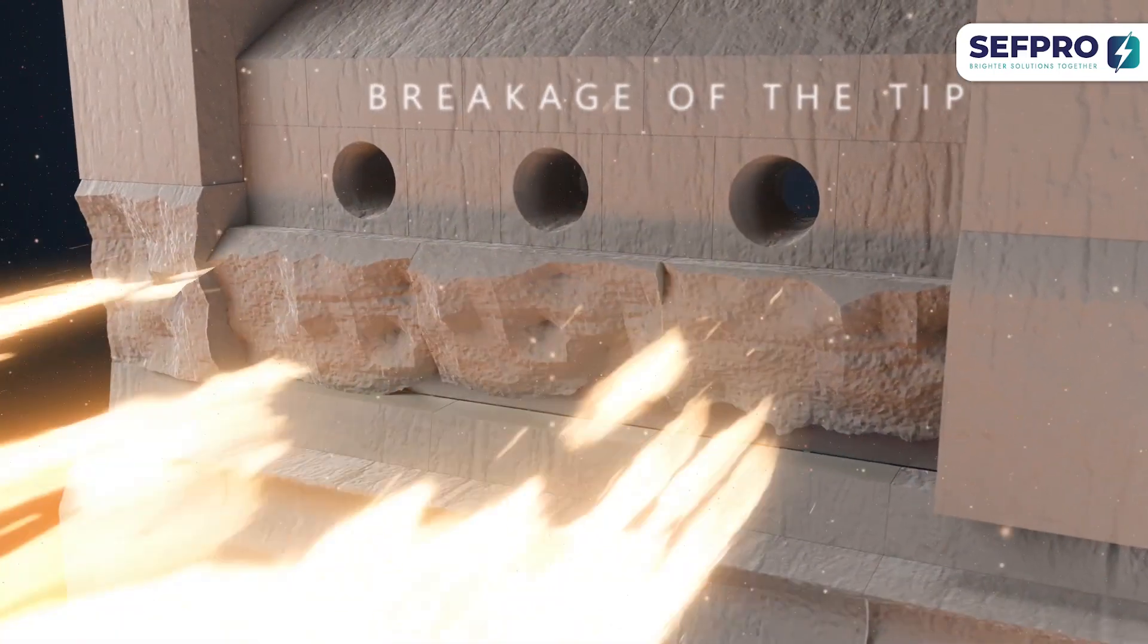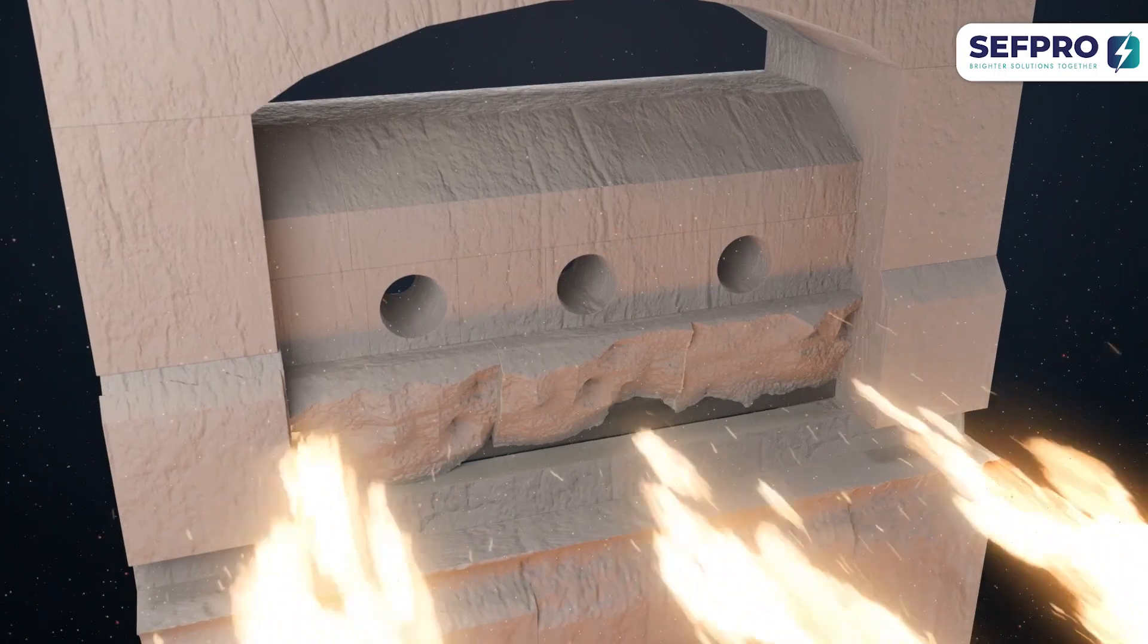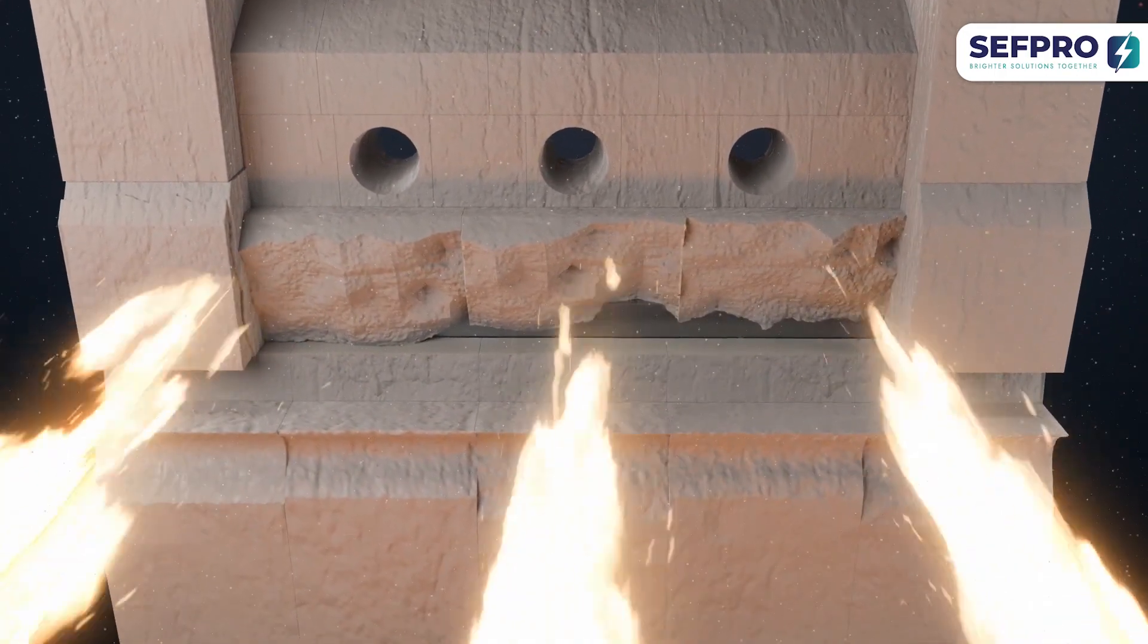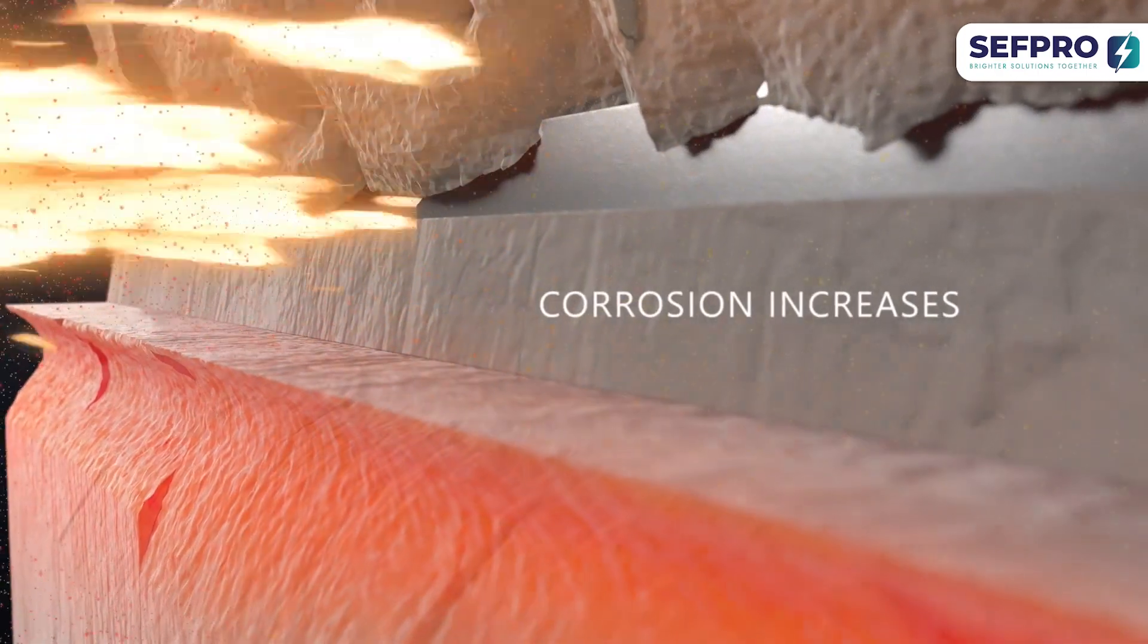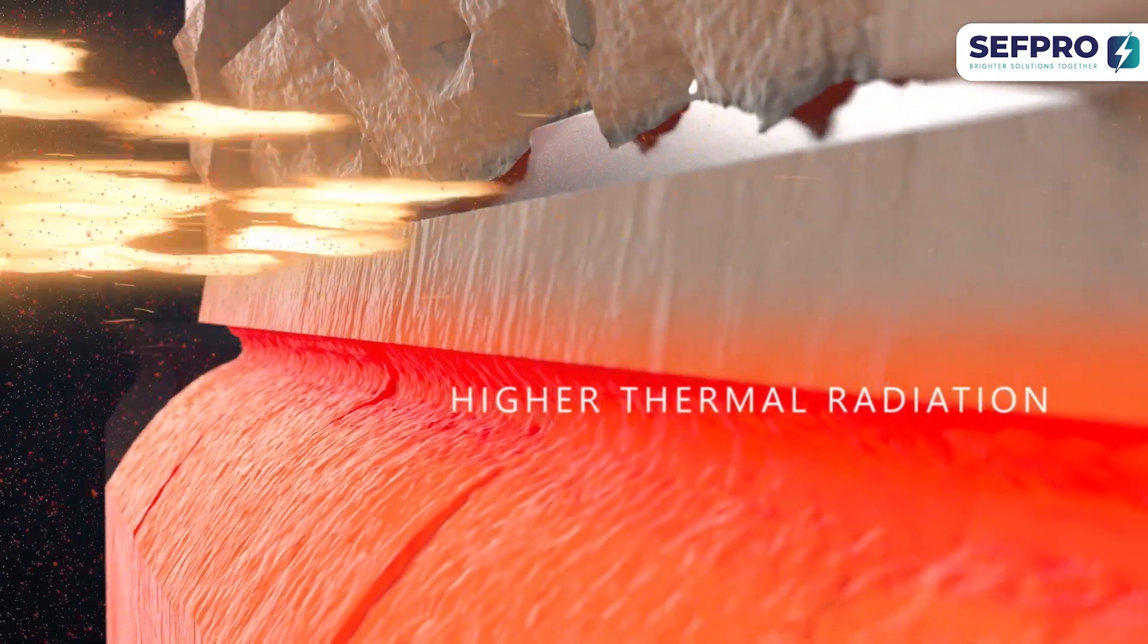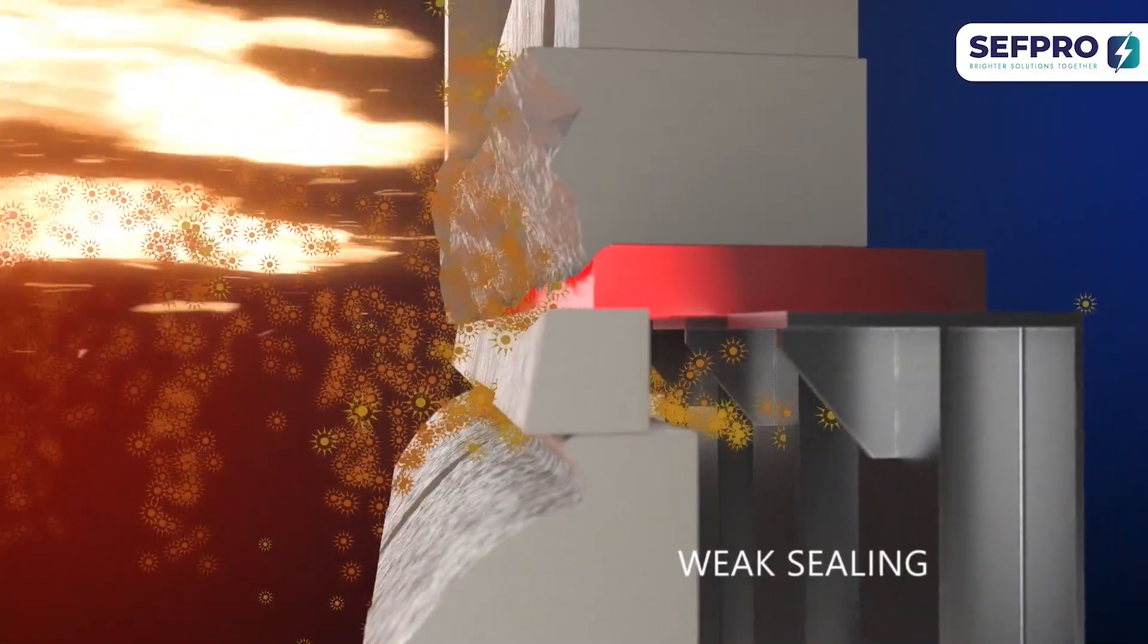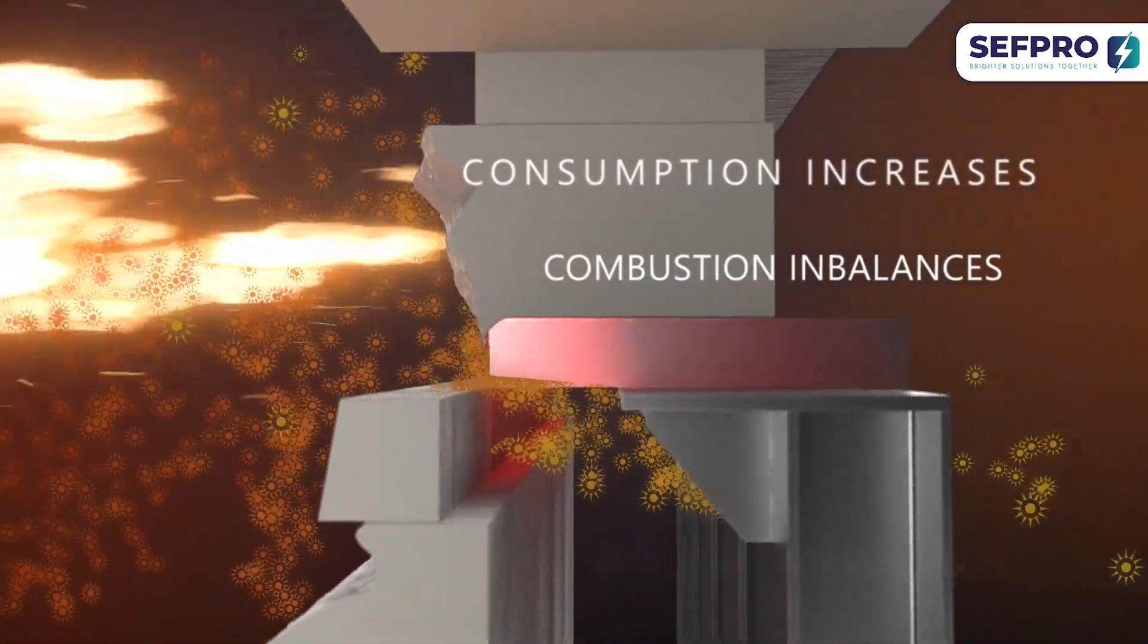The consequences can be dramatic. Tuckstones damage is the beginning of severe trouble for your furnace. Without the protection of the tuckstones, sidewalls corrode much faster as they're exposed to higher thermal radiation. Besides, your furnace sealing becomes less efficient, resulting in increased fuel consumption.